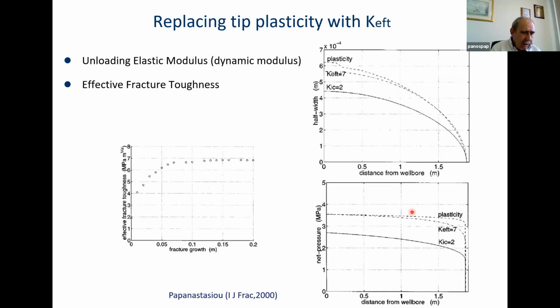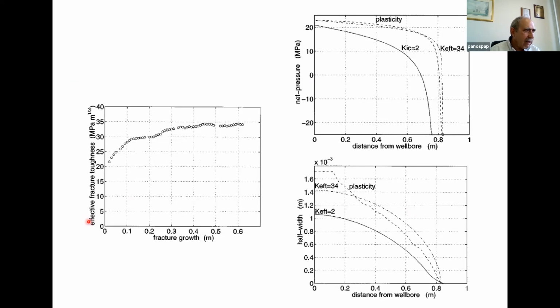And I have another example where the effective fracture toughness this time was 34. It was for a much weaker material. So we got an effective fracture toughness of 34 megapascal root meter. And then we use this elevated elastic modulus. At the top we have the pressure profiles in the fracture, which is quite close again to plasticity. And in the lower, we have the fracture profiles.